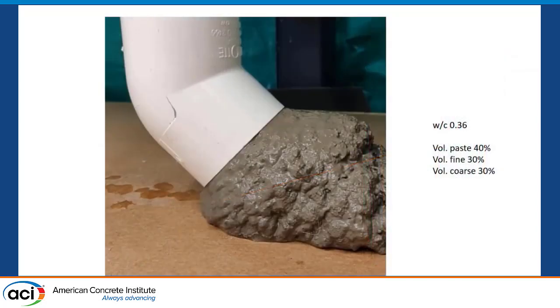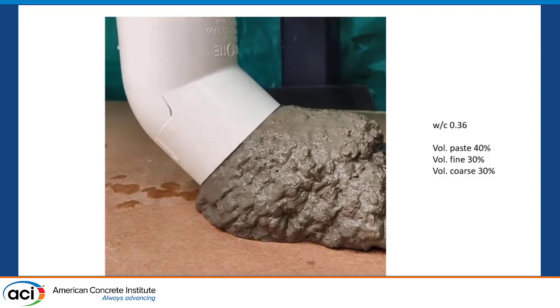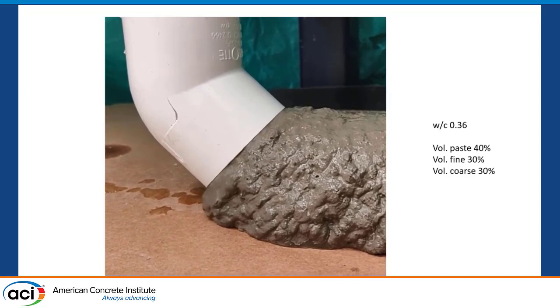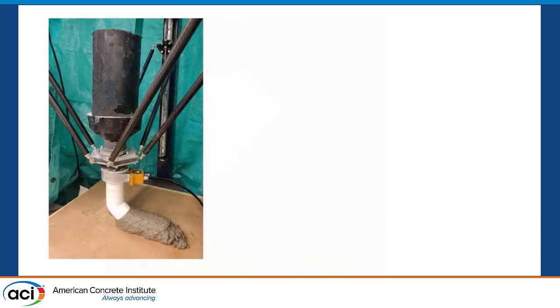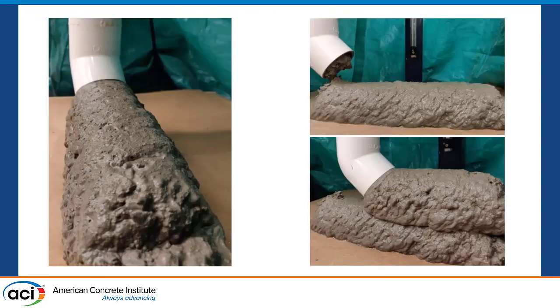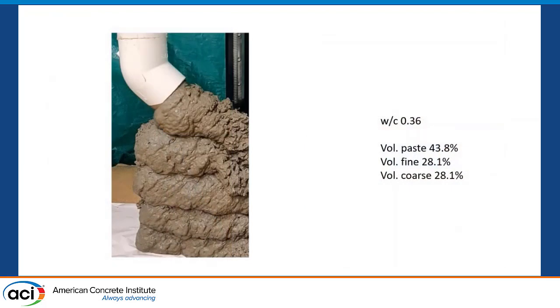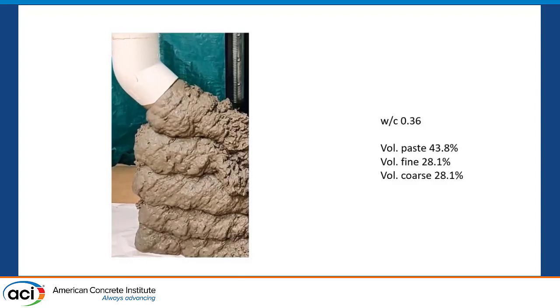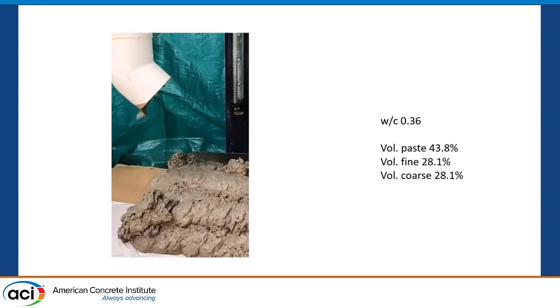Let's see if it actually works. You'll hear the vibration motor sound, and you'll see the specimen coming out and still holding its shape — that's what the process looks like. When I'm not vibrating, on the top right you see no material is coming out. I'm able to place multiple layers. Even though my experimental protocol with the ICAR was 15 minutes, here it's actually just 30 seconds before the nozzle comes back to the same spot. It still has enough yield stress to hold its own shape, both in the longer direction as well as in the horizontal direction. However, not all mixes behave the same way — with paste increased very slightly, after about five layers, it's actually failing.